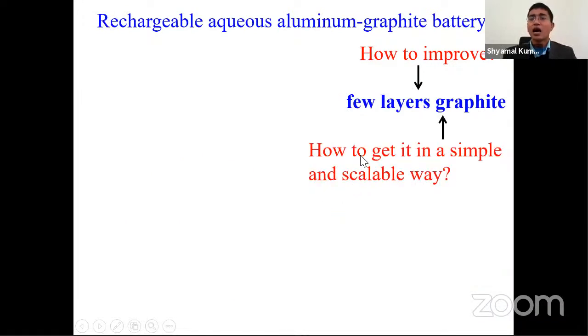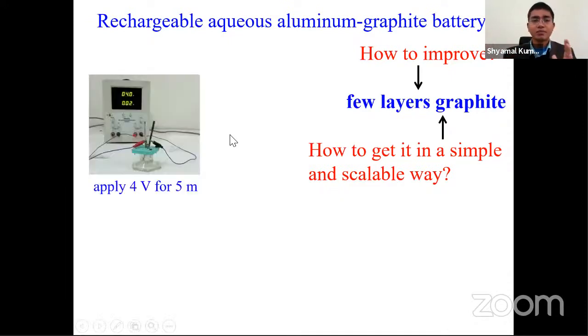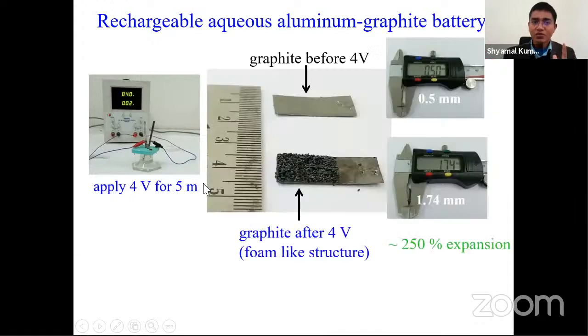Now, how do we get that few layer graphite in a very simple and scalable way? It is very simple. What we did is we took our cell and applied a DC potential of 4 volt for 5 minutes. When we did that, you can see the structural change of the graphite. This is the pristine graphite before the application of the 4 volt, and this is the graphite after application of 4 volt. As you can see here, it is a foam-like structure, and there is 250% expansion of this graphite foam compared to this graphite.